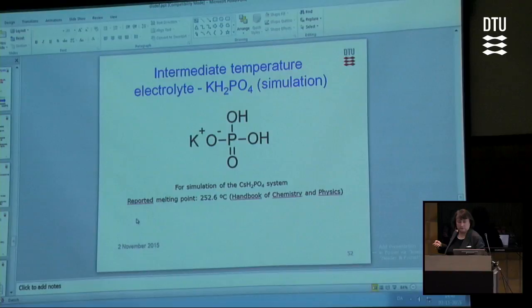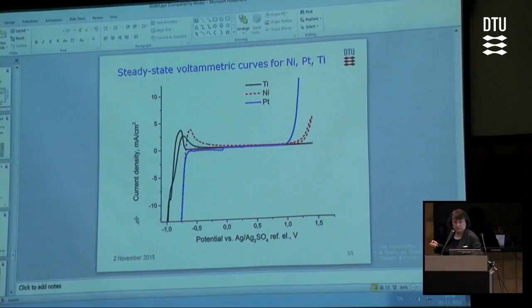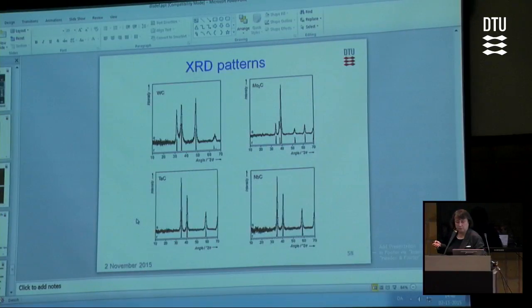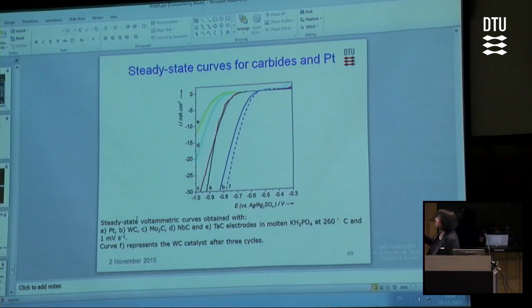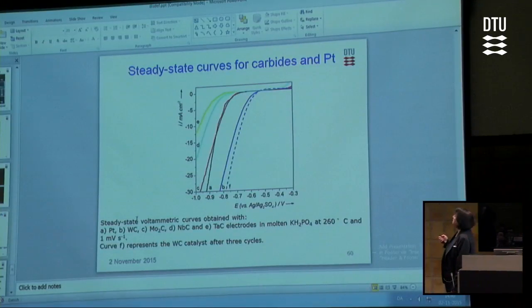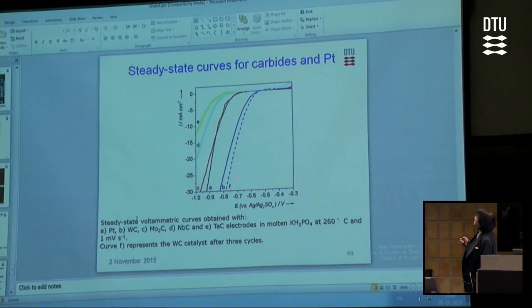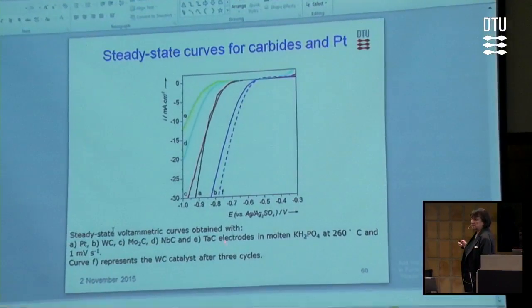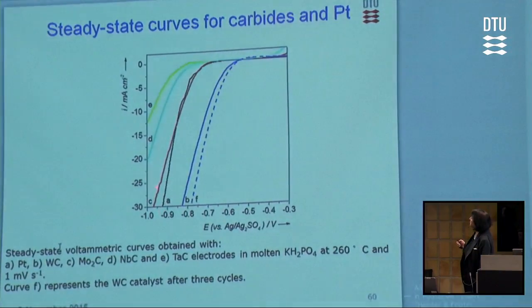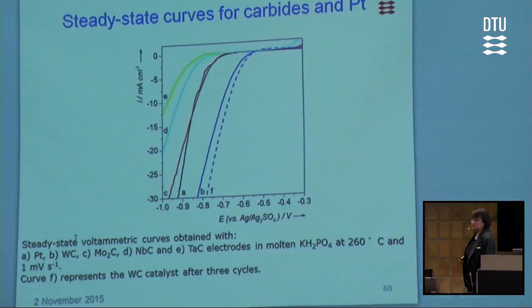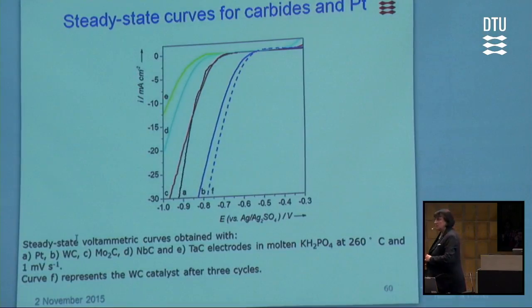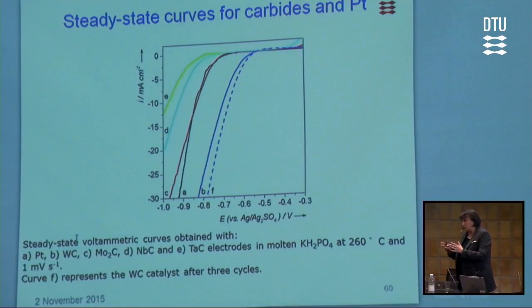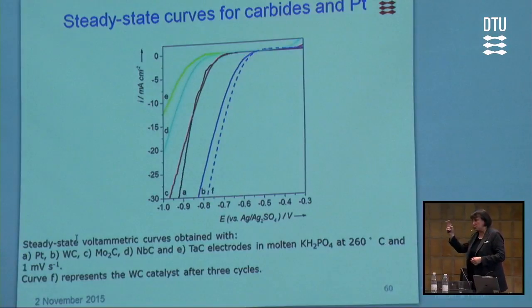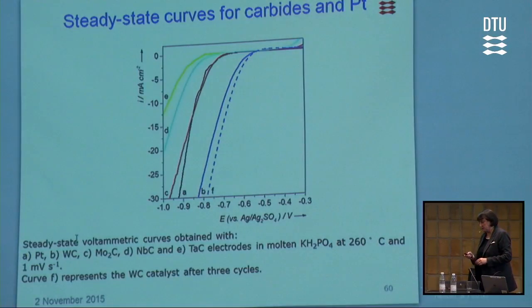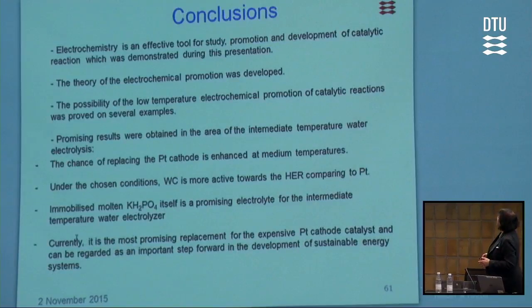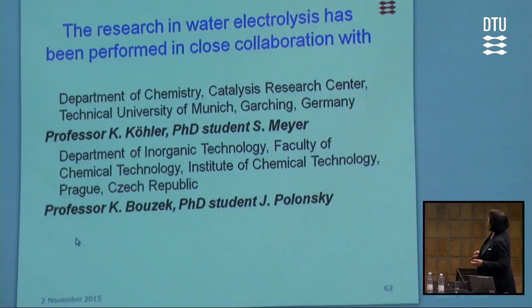With our German colleagues from the Technical University of Munich, we proved 100% that in this molten salt, tungsten carbide has much higher activity for hydrogen reduction than platinum. This is after several cycles. So, big hope. Another hope: nickel is stable, so we can use nickel oxide on the other side. Very cheap. Okay, those are my conclusions.